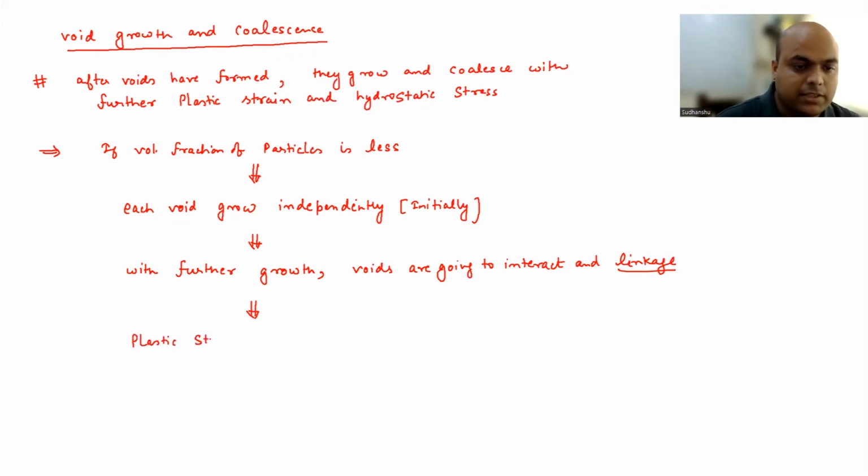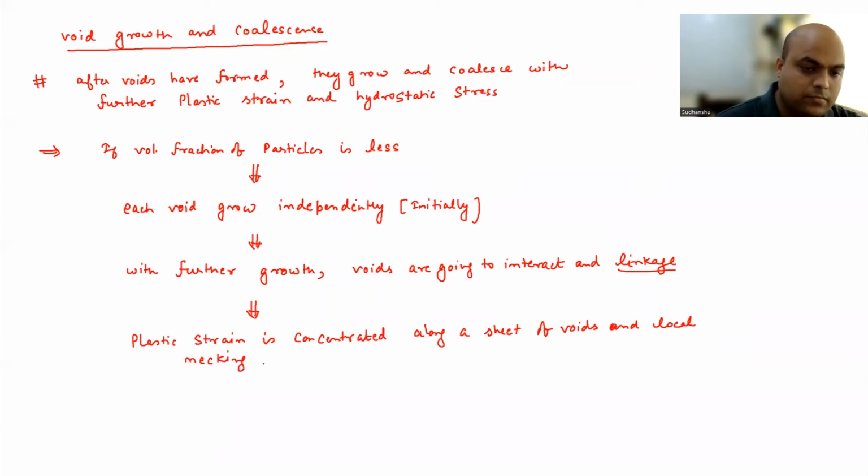So plastic strain is concentrated along a sheet of voids and local necking instability develops.